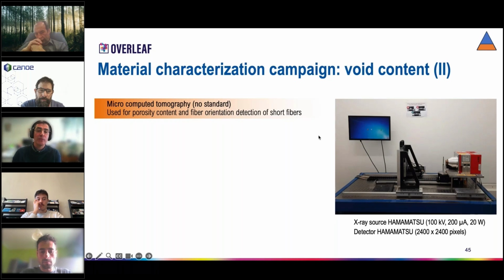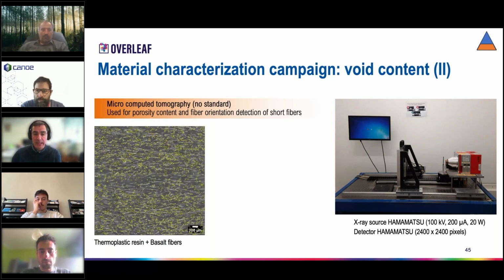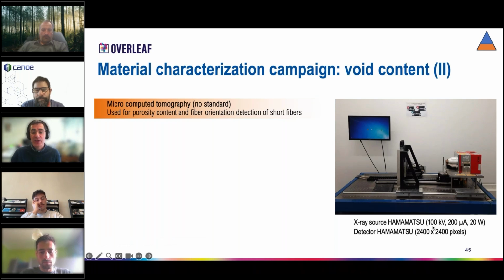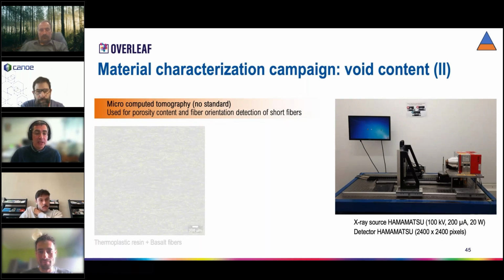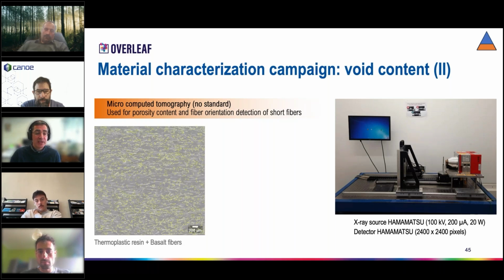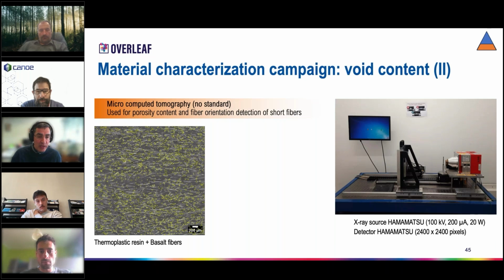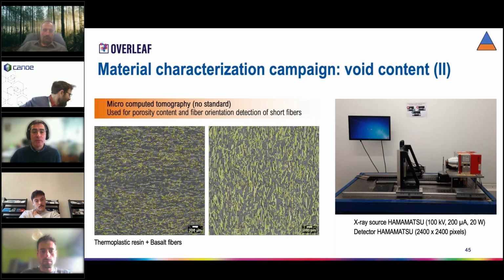All these studies also have been complemented with microcomputed tomography. In that case, we have an equipment with an X-ray source and a detector. Here on the right side, you have more or less the main properties: voltage, intensity, power, and the size of the detector. And we use this equipment for porosity content and fiber orientation detection. So here I have a couple of images for the thermoplastic resin plus basalt fibers in which we detect the porosity. Here you can see in black small holes. And on the right side, if it loads, we can see the fibers. So we can detect, for example, the percentage of fibers oriented at 0 degrees or according to the printing direction, apart from knowing the percentage of the fibers.